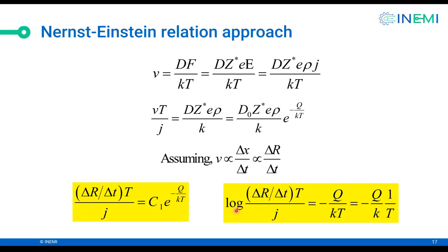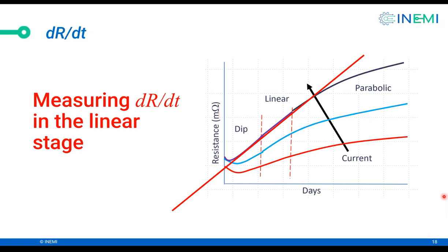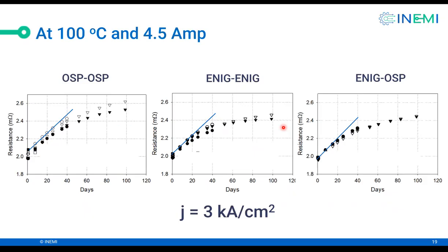So essentially, we plot the log term versus 1 over T. But getting back to what rate of change of resistance do we use? So we stay with the linear region. And then this is actual data. So this is 100 degrees centigrade, 4.5 ampere current. And you can see the curve is parabolic and there is no dip. The reason there's no dip is the current is too high, so the dip is very short. So we just take the slope of these curves as a measure of electromigration.